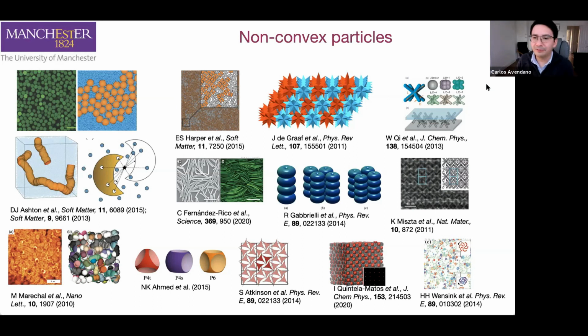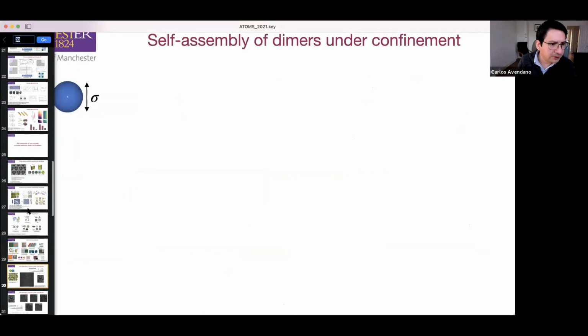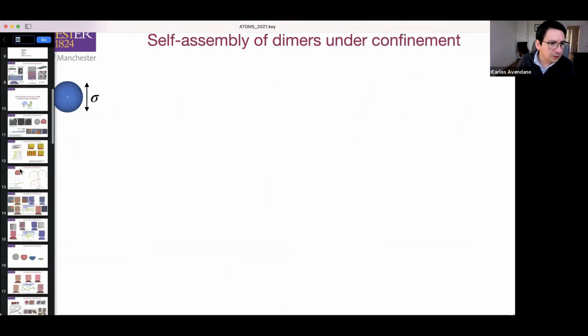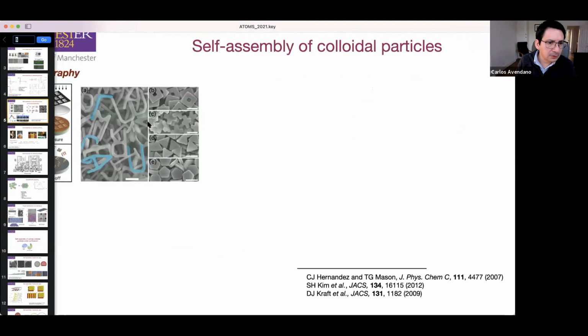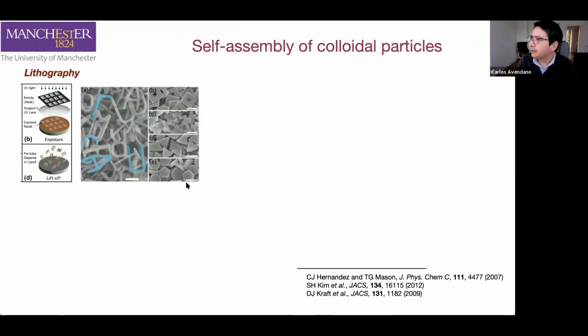So the first question of Richard is, what is the length scale of the particles of Thomas Mason? So this error bar, if I remember, is about 20 microns. You are always moving almost to one of the extremes of what you call a colloidal particle, but they actually observed that there was still Brownian motion at that scale. So yeah, that was about 20 microns. And I think the minimum scale that they presented in the experiment was about 4 microns, if I remember correctly.